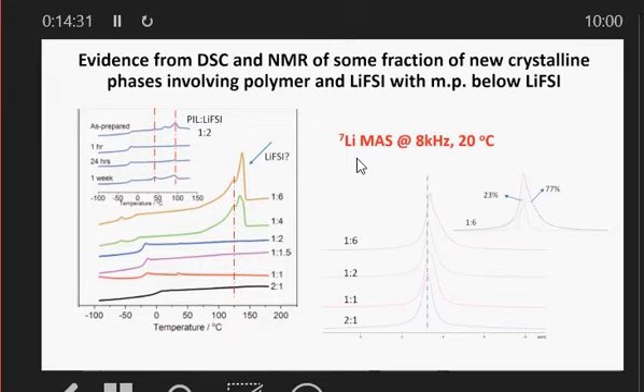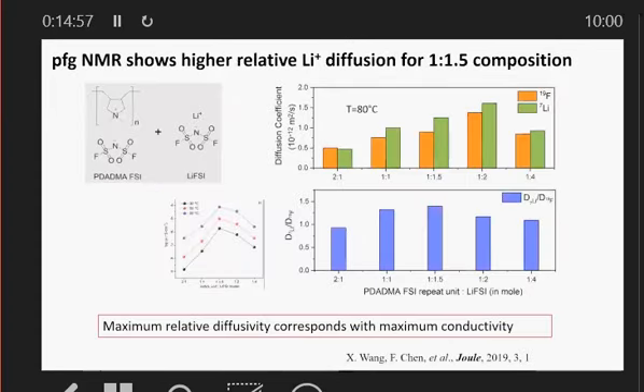And that's also clear to us when we look at the NMR spectra on the right-hand side for the different compositions. In the magic angle spinning for lithium-7, we see multiple lithium sites. Lithium has a very narrow chemical shift range, but nevertheless, we can see that different sites are appearing. So this means in the polymer itself, in the electrolyte, we have multiple environments for the lithium. And in some cases, this environment gives you optimum conductivity. In other cases, we lose some of that dynamics. So let's go further and see if we can understand what's going on here.